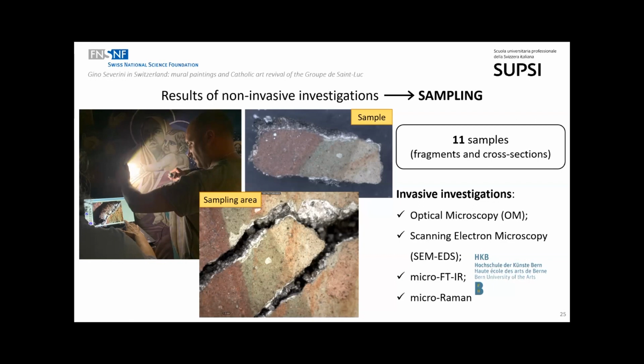to obtain cross-sections. Then invasive investigations were performed, in particular by optical microscopy, to visualize the stratigraphy and to measure the thickness of each layer, by scanning electron microscopy to observe the different morphology of the paint materials and elemental composition, and then by spectroscopy techniques like FTIR and Raman, that with the use of a microscope allowed to focalize the measure in specific, very small points.